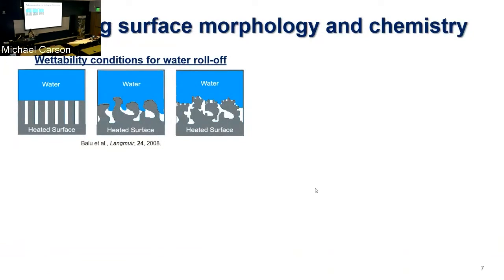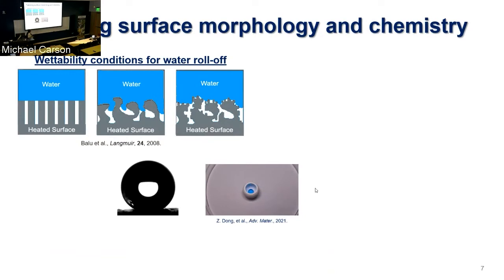We can continue to really modify these surfaces to give us different types of precipitation and allow us to extract different resources. So here what I'm showing you is essentially modifying the surface material by creating hierarchical roughness. What this allows you to do is, if you have a combination of micro and nanoscale roughness on surfaces, you can really create hydrophobic and superhydrophobic surfaces that prevent the salt from precipitating at the surface and also promote the water to roll off from the surface. You can get very high contact angles with these modified surfaces. And as you can see here, as soon as you deposit a droplet, it beads up and it really does not spread on these modified surfaces. So you get almost this rolling off behavior from these hydrophobic and superhydrophobic surfaces.